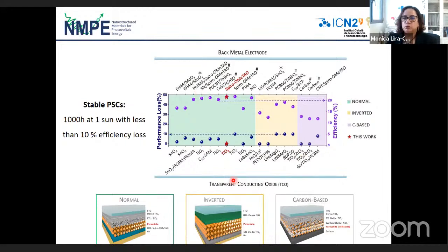However, this is only to show you that we still have to find what is the key to obtain these materials as stable. For example, people talk a lot about the instability of spiro. However, you can find this material as the transparent oxide, this is one transport layer, and this is the opposite transport layer. You can have all types of solar cell: normal configuration, inverted, or even carbon-based. These are the most stable perovskite solar cells. You can find almost any material here, you can find spiro, you can find C60, all types of materials. So it's not very clear exactly what is going on in the solar cells and what is affecting the stability of these devices.